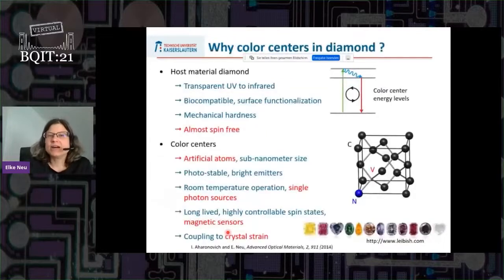Okay, so let's start right away with why we use those color centers in diamond as sensors. The color centers are defects in the diamond where you have just changed the lattice in one or a few neighboring lattice sites. The most prominent color center is the so-called NV center. So you have a nitrogen replacing a carbon and a vacancy. This forms the defect. And for us, this defect is an artificial atom. So it more or less acts like an atom. You have electrons bound there. It is very stable, which is good for a sensor. And the point that we like to use is that it has very long-lived and highly controllable spin states, which makes it an interesting system for a magnetic sensor.